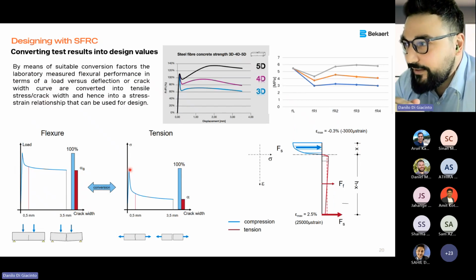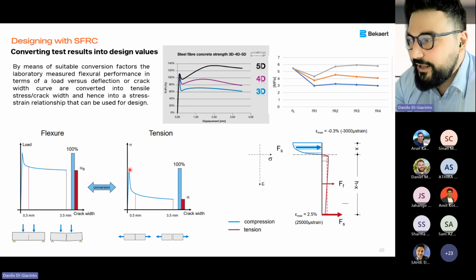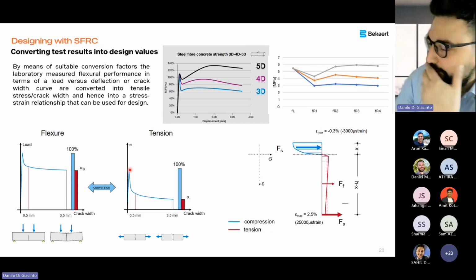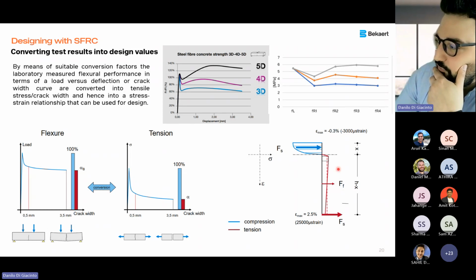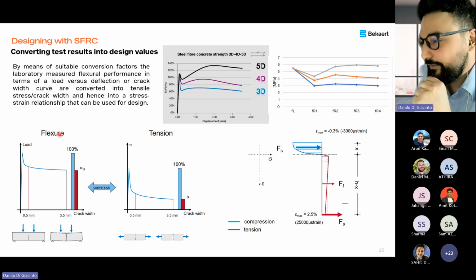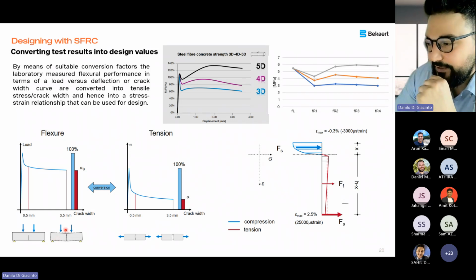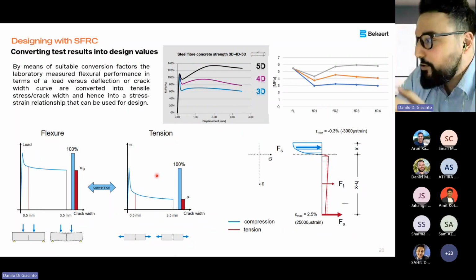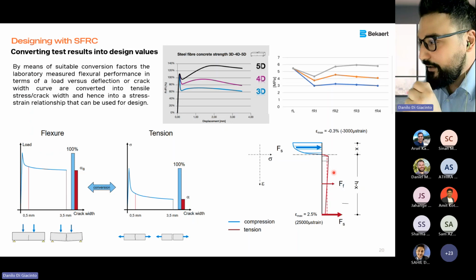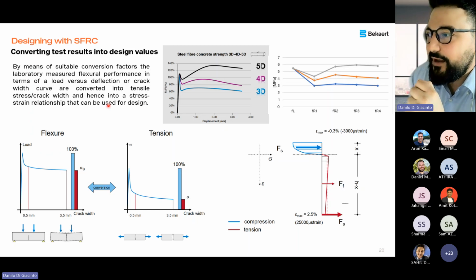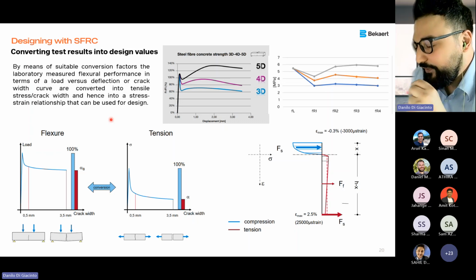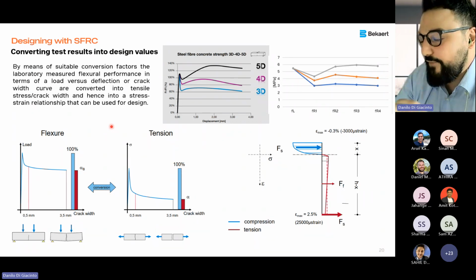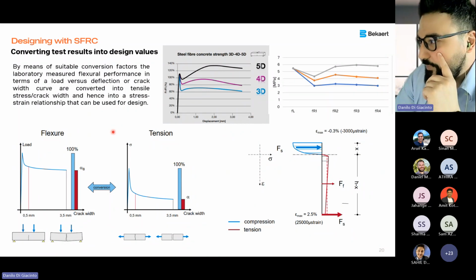And at the end, when it comes to design, it's passing from a flexural behavior to a tension behavior. This is what you use in cross-sectional design to get the moment capacity. So what you get from characterization of the material, the three-point bending test I showed previously, is converted to the tensile load, which is what you use for the concrete below the neutral axis. It's just a matter of applying the right coefficients. Those coefficients are listed in the standards that you are using. And obviously, we have a very vast background and experience on that, and we can help you.